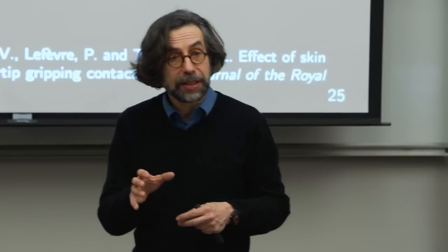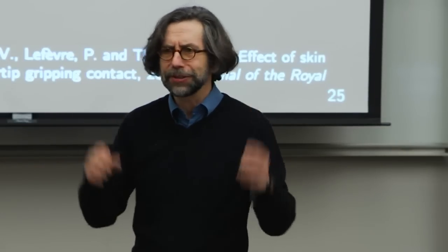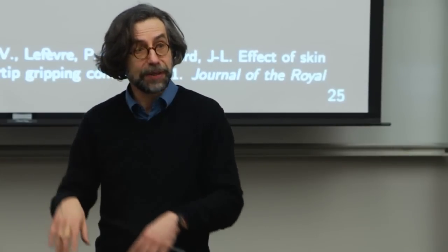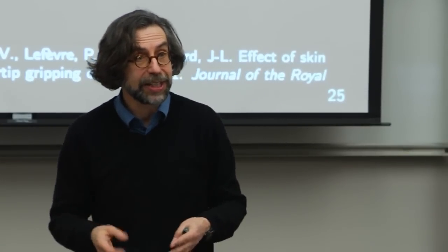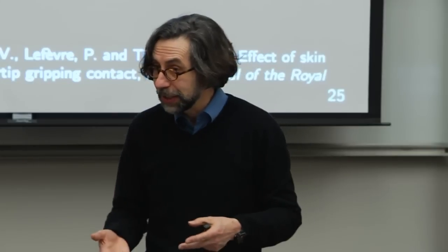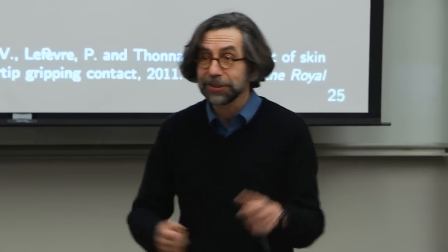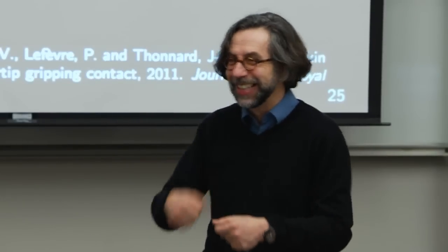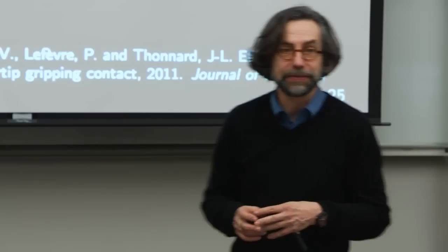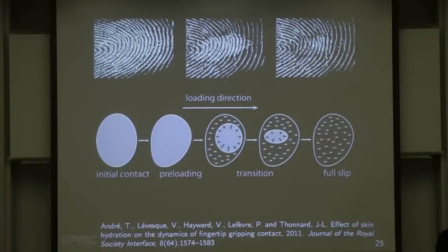And so the influence of time and water on the grabbing act is much bigger than your squeezing force, by a huge factor. So basically it doesn't matter what you're doing, time is more important. And the second category is objects which are porous, and they do the opposite. They take water away. When you do the measurement, you find that through time, your grabbing capabilities are lower. Which we all know when we read a newspaper. First page is okay, and the second page is slippery, and the third. And that's true of wood, of fabrics, and all these other kinds of objects, where you have to replenish water. So I'll finish on that.